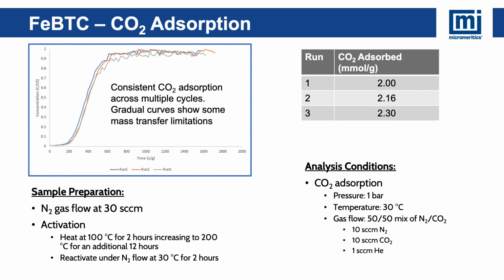And lastly, looking at iron BTC, once again, we see consistent CO2 adsorption across multiple cycles. However, compared to the other materials where we saw very steep breakthrough curves, this one is a little bit more gradual, as we see some amount of mass transfer limitations in this material. However, once again, we see fairly consistent CO2 adsorption across multiple cycles, such that we're able to reactivate this material without heat.